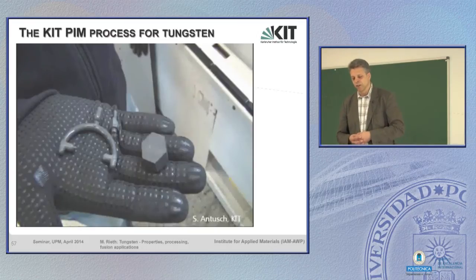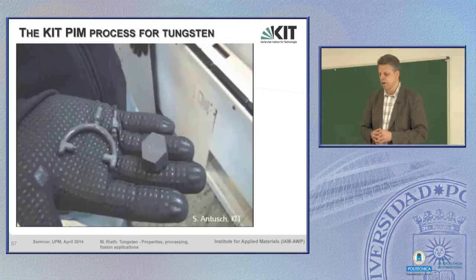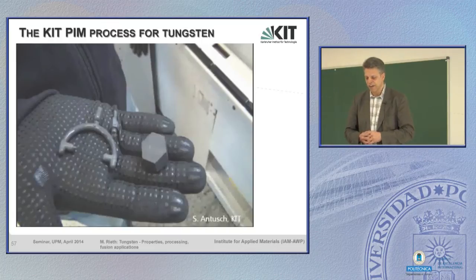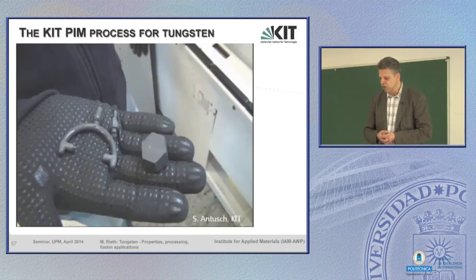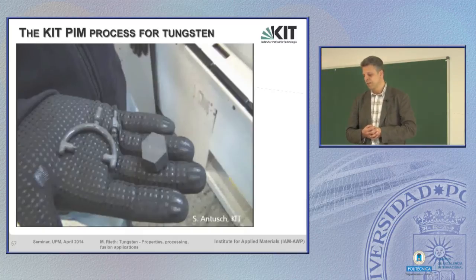Here is how it goes or looks like. This is a machine with a filled tungsten powder binder feedstock. Here you see one half of the tool. This produces hexagonally shaped armour parts. That's the other part of the machine. Then the tool is pressed together. Then the feedstock is injected into the tool. This happens at around 200 centigrade or so. That's enough, but with a high pressure. And so finally you end up with the green part.